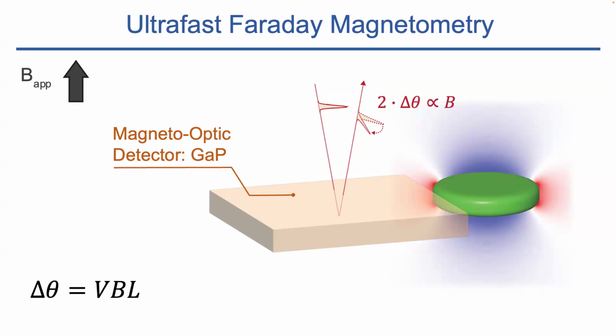Now, the Faraday effect is an effect by which if you go through a magneto-optically active material with a pulse, you'll have a polarization rotation. This is either in transmission, or twice the polarization rotation in reflection, that is proportional to basically the magnetization inside the material, but let's say the magnetic field. Because you want this to be fast, you cannot use a ferromagnet because this will depend on the precession of the magnons. So you use a diamagnet, and the Verdet constant that gives me this rotation drops by many orders of magnitude. And yet, if you're careful enough in the way you measure this polarization rotation, you'll be able to measure the magnetic field around here.